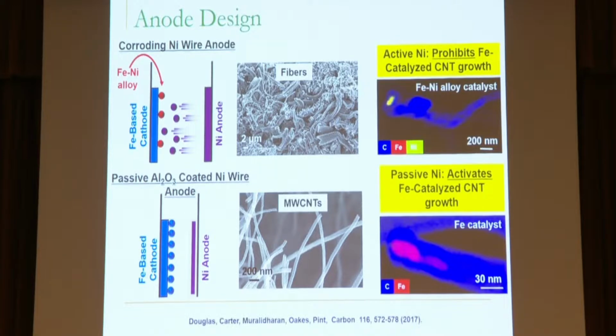If we make these little fiber things, if we use this setup, with a nickel anode and some steel-based cathode, right? And what we found is that always, so this is looking in the electron microscope again, and we're using a process called energy dispersive X-ray spectroscopy that allows us to see the chemical identity of the materials. And so you see this looks like nickel, but we're growing the carbon. The carbon is being deposited on this iron-based cathode. Where's the nickel coming from? It's crazy.